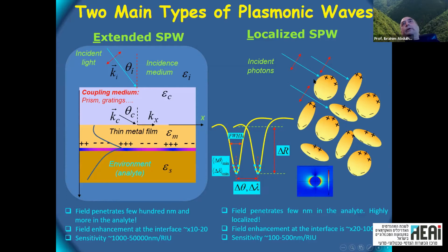But the surface wave then is localized on the surface of the particle, and cannot propagate along the metal film, as in this case. So that's why it's called localized surface plasmon resonance. In both cases, we are looking for a minimum in the spectrum. Let's see, in this case, we look for reflectivity, and we see a minimum if we scan the angle or the wavelength. And this minimum is very sensitive to the environment, the refractive index of the analyte medium. The same with this one, but here we don't do it as a function of angle because it's scattering and does not,